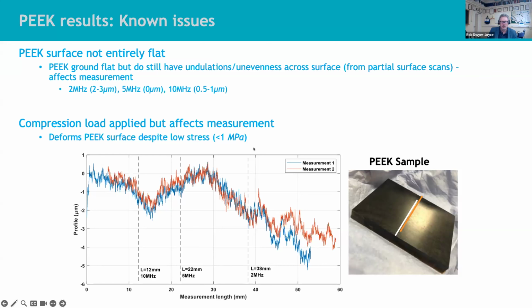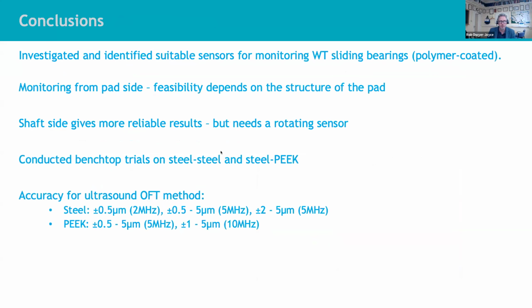And compressing it also deforms it. Even though these are quite low pressures when we're compressing it in the test rig, it deforms the surface. So there's an uncertainty about what the oil film thickness actually is in reality.